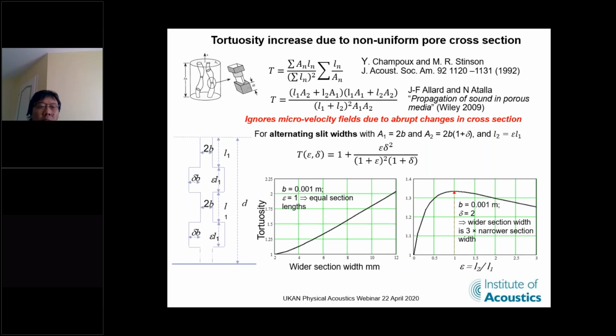So they had created cylindrical pores and non-uniform cylindrical pores. I've looked at a much simpler example where you create non-uniform slits. And I've looked at how the tortuosity would vary for this very simple system according to the parameters in the system. And not surprisingly, it turns out that within the range of parameters I've looked at, if you have equal lengths for your different cross sections, then that gives you the highest tortuosity.